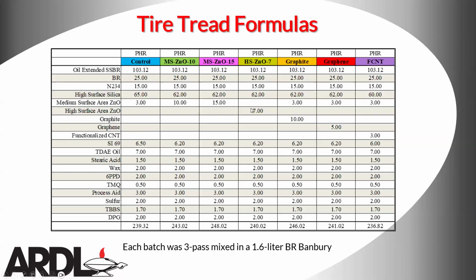And then we went back down to our 7 parts, but here we're looking at a high surface area zinc oxide, so something that's a little bit more active. And then we looked at graphite, where we replaced 3 parts of silica with 10 parts of graphite. And then when we did graphene, we replaced 3 parts of silica with 5 parts of graphene. And in the carbon nanotube, we used a functionalized carbon nanotube. We actually replaced 5 parts of silica with 3 parts of the functionalized carbon nanotubes.